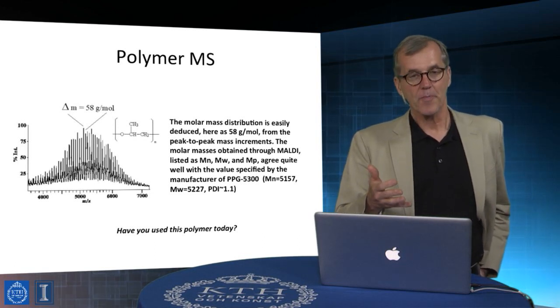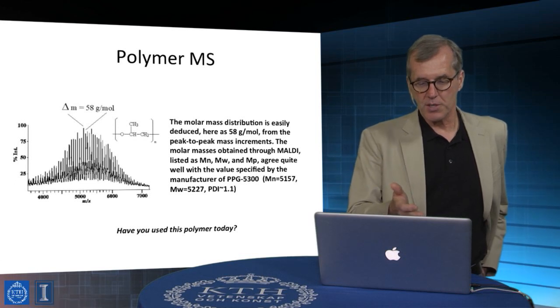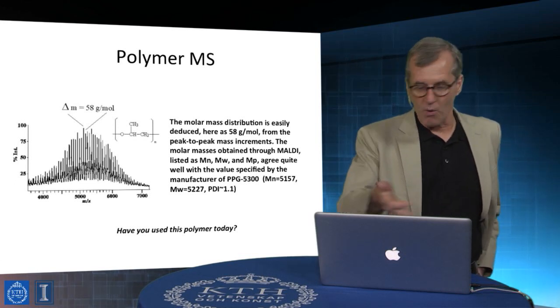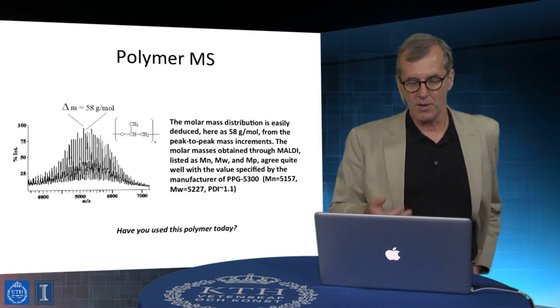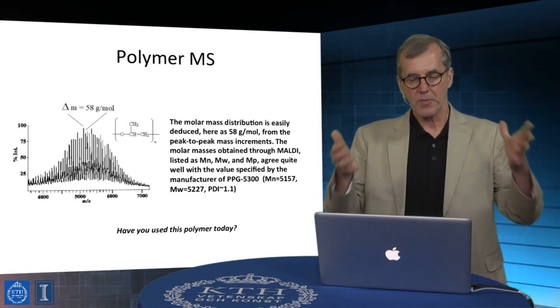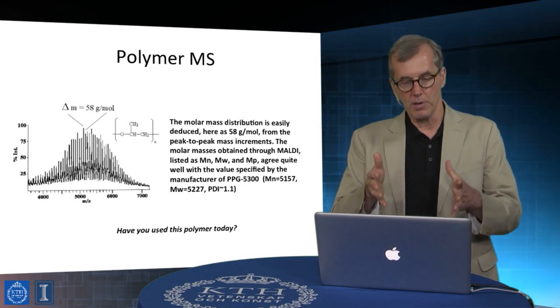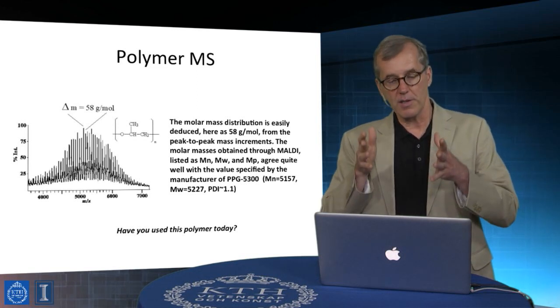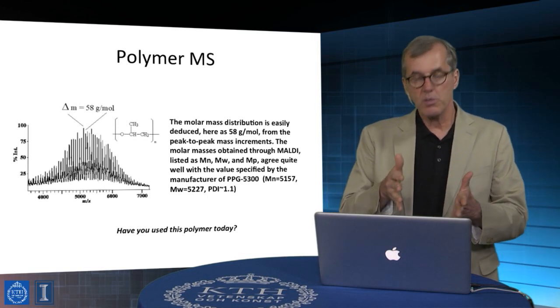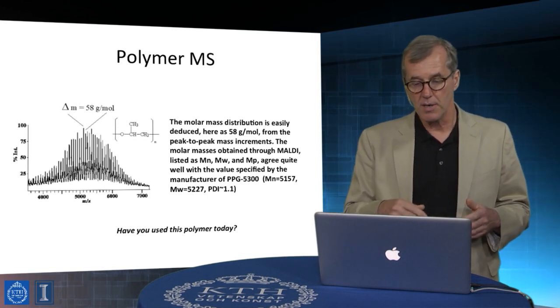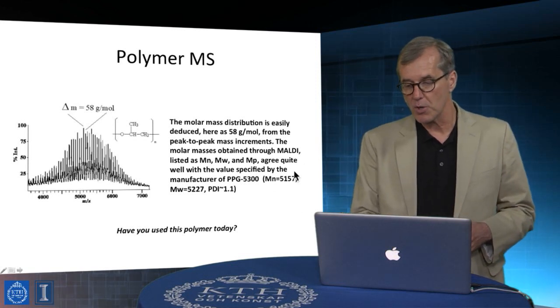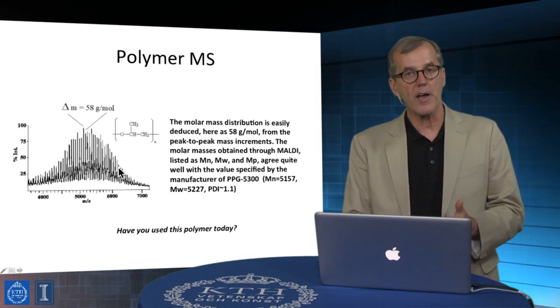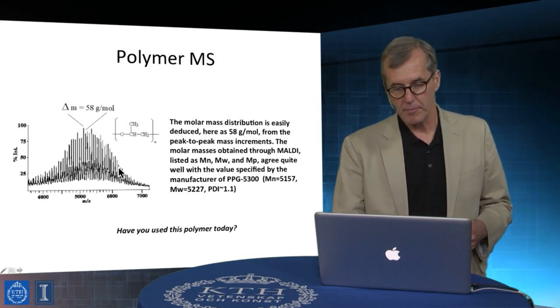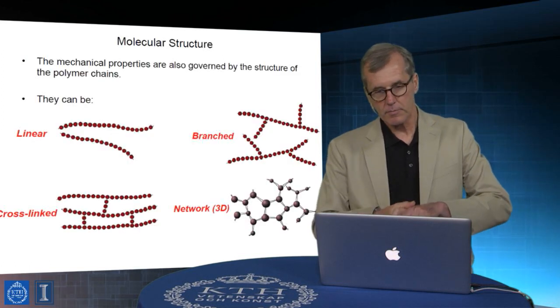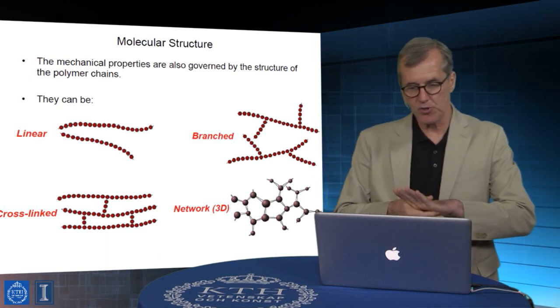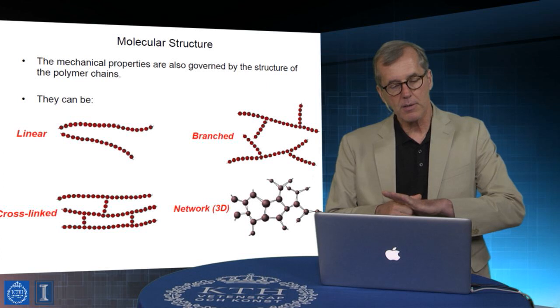But here we see that, in point of fact, we actually see the charge to mass characteristics of all the things that are present in the sample. This is not the fragmentation of the molecule. This is actually the amount of material that's present with all these different discrete masses. And we can actually use this data to construct the polydispersity index level analysis that's shown here, just by quantifying what's seen in the mass spectra. So that's very powerful.